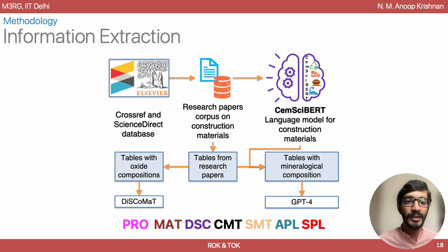So in this particular framework, what we have done is we have taken a lot of research papers on construction materials, and we developed a language model called CemSciBERT for cement by training it on a corpus of around 100,000 papers in the domain of cement and concrete. And then we have taken text and tables, and for tables with compositions we have extracted using a framework called DiSCoMaT, which we developed. And if you have tables with mineralogical compositions, we have extracted using GPT-4. So you can now see how easily information can be extracted from literature.